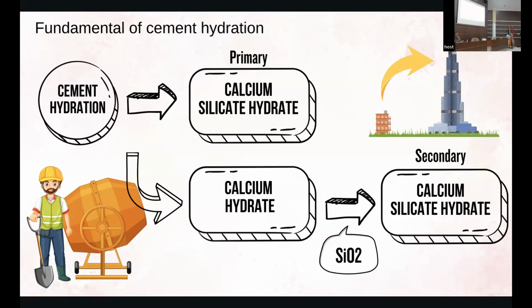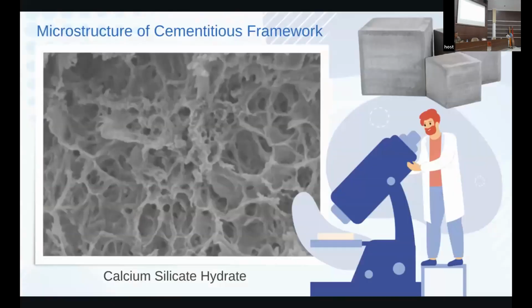Now, what if you can convert this calcium hydrate into secondary calcium silicate hydrate by including silica in the middle of it. So this silica inilah yang datang dari fly ash, datang dari silica fume, datang dari rice husk ash. So all this will contribute to the secondary calcium silicate hydrate. So from here, people can build from like 1, 2, 3, 4 stories building into the Burj Khalifa, for example.